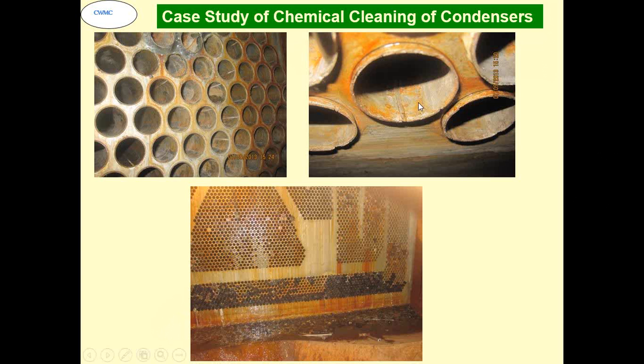Now, in this particular case, what had happened, the plant had fly ash silos along the cooling water system. So fly ash used to fall inside the cooling water, and then it started choking the condenser tube. So below that, a reducing atmosphere is created. As we all know, stainless steels remain stainless steel so long as they are in an oxidizing atmosphere. The moment the atmosphere is reducing, it behaves the same way as a mild steel system.